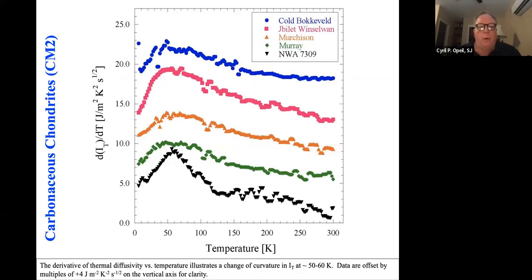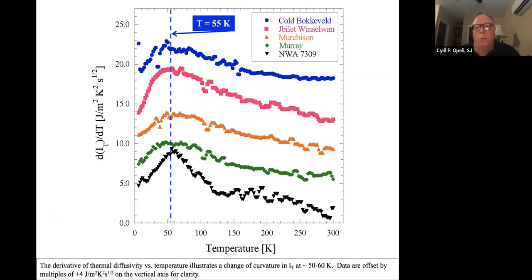And so I took the derivative of the thermal inertia. What we see is that around 55 Kelvin for all the materials, all these CM2s, there's a peak. It's more defined in some than in others. This is probably mostly from the C sub P, specific heat capacity data, where there's actually a change of regime in terms of thermal properties. No one had actually measured any of these below 100 Kelvin before, so it's important to note that the regime change is happening around 55 Kelvin. And then again, this is decreasing rather significantly.